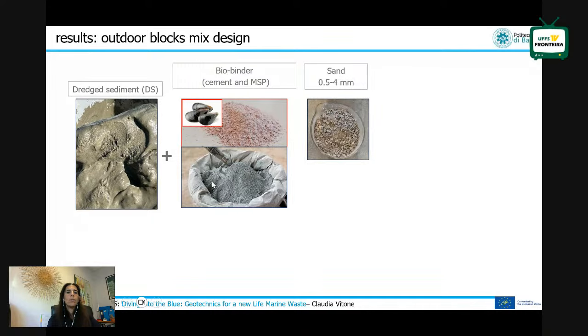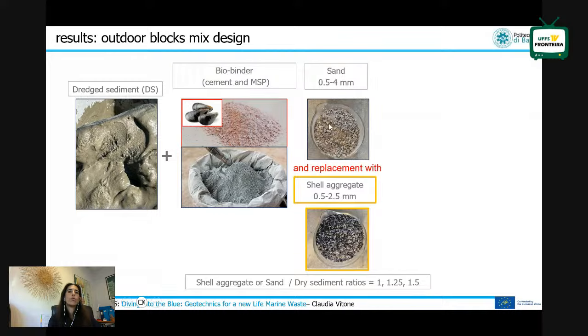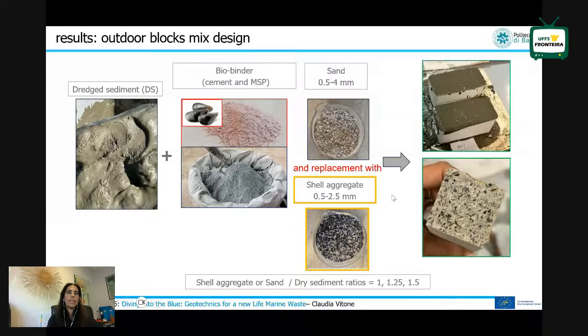So what we did was, of course, to replace these primary materials with our materials: dredged sediments, the cement, which is, as you will see, in a very small amount, mussel shell powder, and also sand. Then, in order to reduce the content of primary materials, we tried also to replace the sand with this shell aggregate, which we have, of course, tailored in order to be effective in replacement of the sand. And we obtained these essentially prototypes of first pavements.